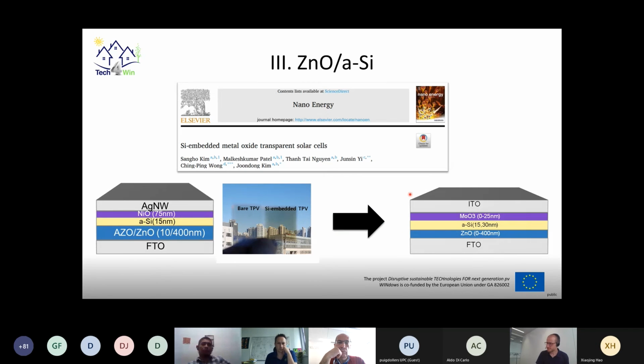And then end of last year, we got an extra idea based on this Nano Energy paper in which they used amorphous silicon embedded between zinc oxide and nickel oxide, where the amorphous silicon, a very thin layer, 15 nanometer, as you can see, increased the performance because the carrier collection improved and also for longer wavelengths. And that's also what you see for the transparency. Bringing in this amorphous silicon layer is reducing the transparency a bit, of course. But still, they had some very interesting efficiency results.